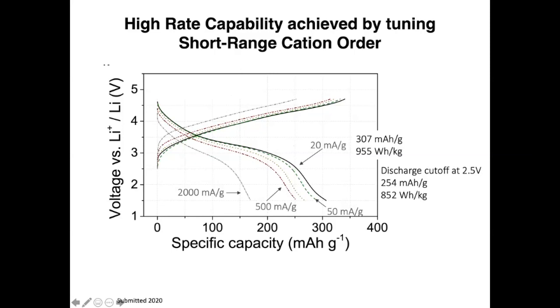So this is important because it means that you can use short-range order to tune the rate capability. And what we have done here, and unfortunately we're not ready to disclose this composition, we, through compositional modification and annealing and heat treatments, we can tune the short-range order to get better percolation and therefore get better rate capability. And here's a DRX material that at 20 milliamp per gram gives almost 1,000 watt hours per kilogram, but holds really good rate capability, in contrast to some of the prior DRX materials.